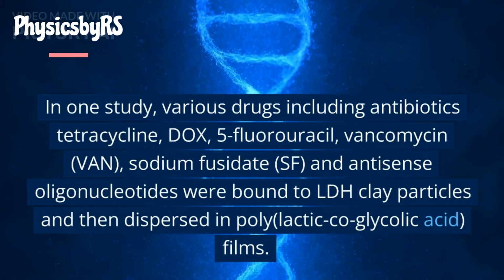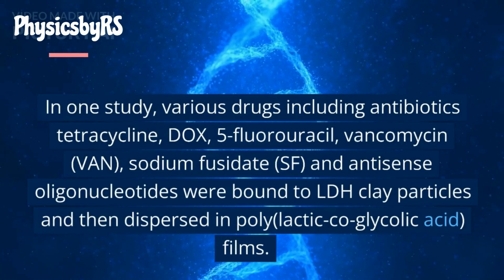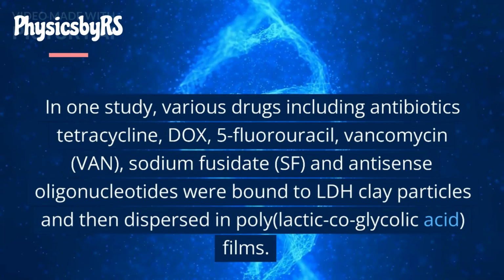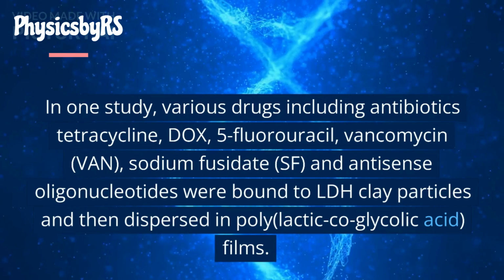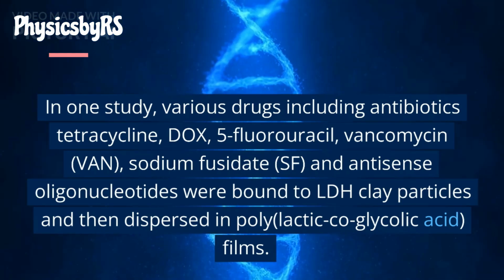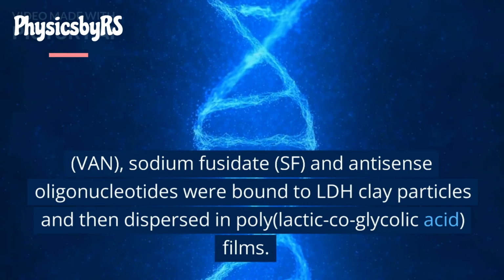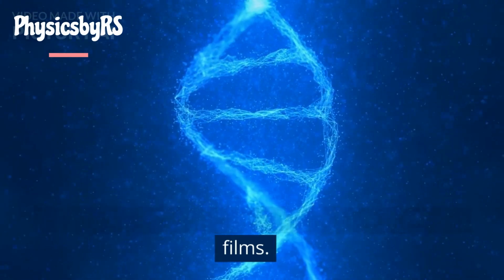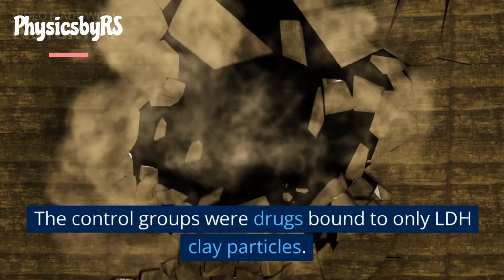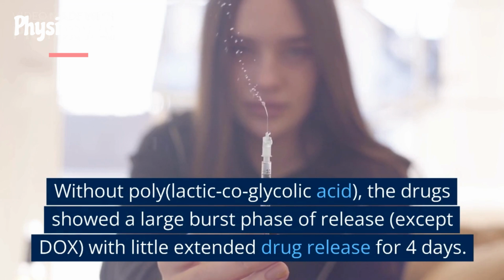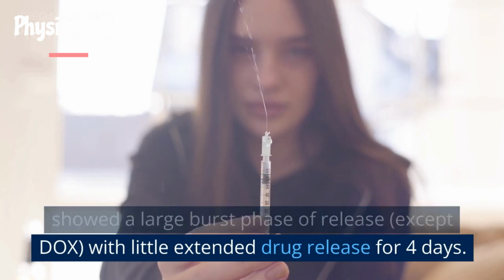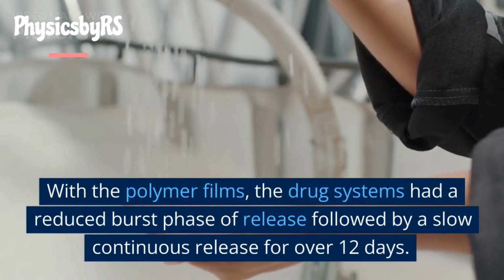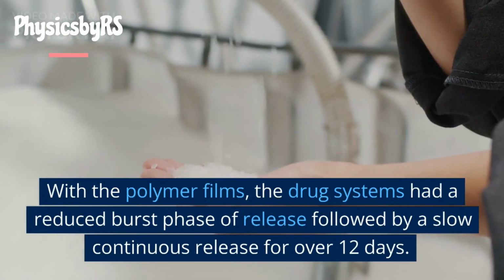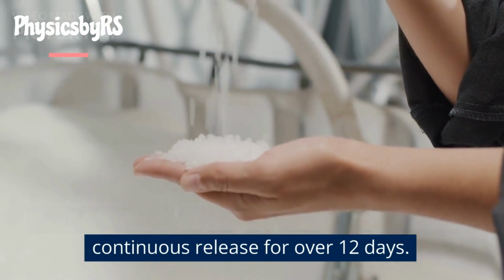In one study, various drugs including antibiotics tetracycline, DOX, 5-fluorouracil, vancomycin, VAN, sodium fusidate, SF, and antisense oligonucleotides were bound to LDH clay particles and then dispersed in lactic co-glycolic acid films. The control groups were drugs bound to only LDH clay particles. Without lactic co-glycolic acid, the drugs showed a large burst phase of release, except DOX, with little extended drug release for 4 days. With the polymer films, the drug systems had a reduced burst phase of release followed by a slow continuous release for over 12 days.